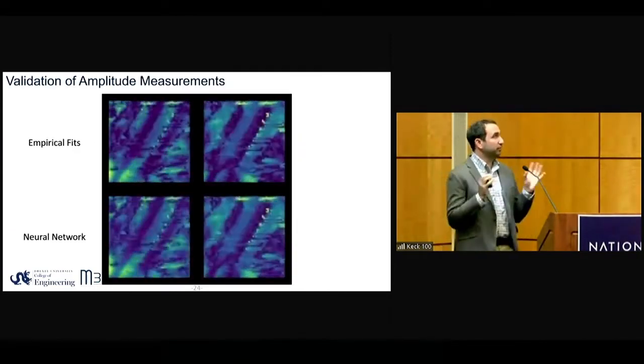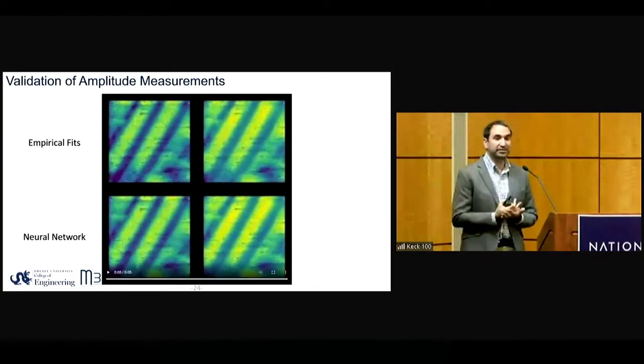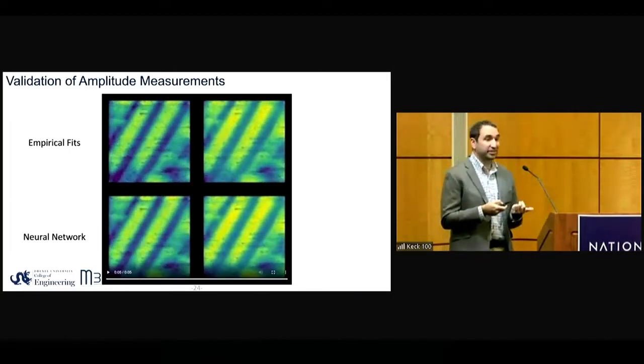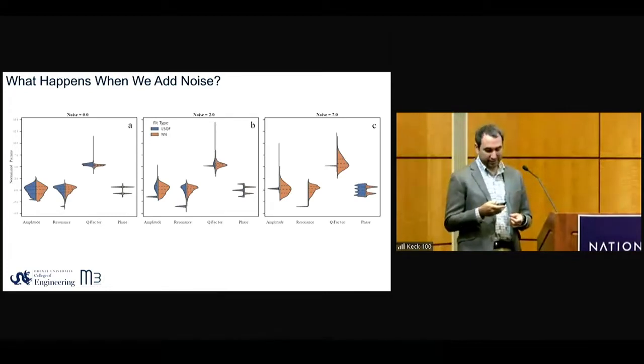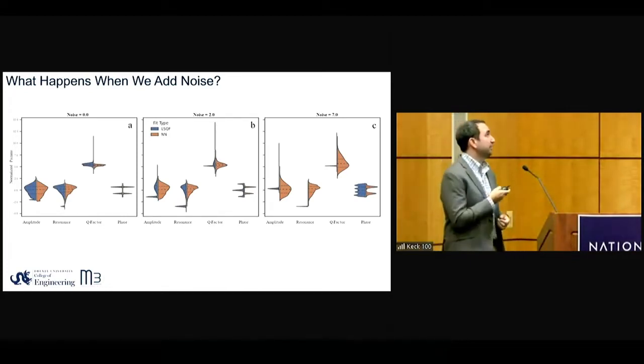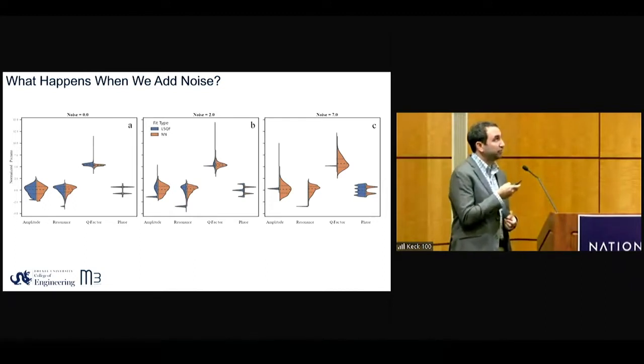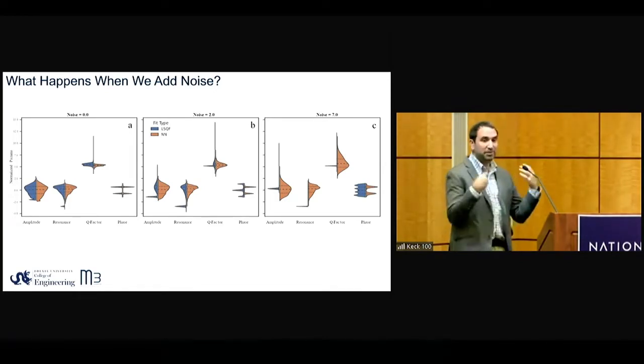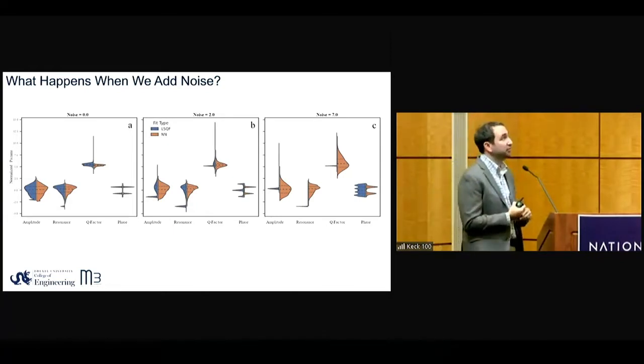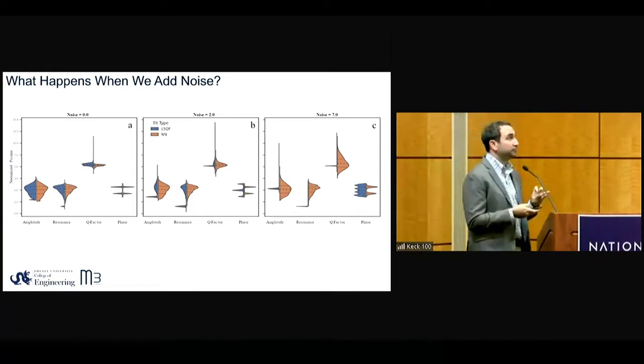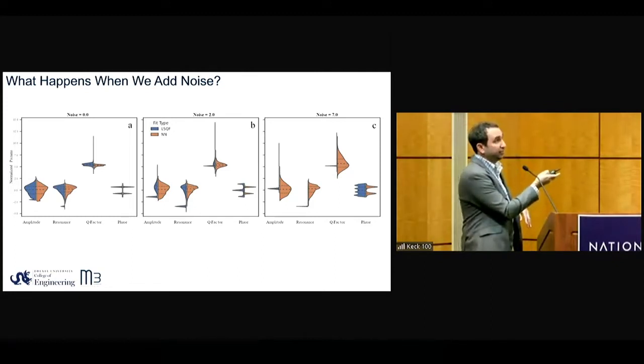If we look at the raw data that a person would extract, it looks essentially the same. There's no difference. So that's a good sign. But things get more interesting when you start to add noise. If you add noise based on the standard deviation of the raw data, you see that as you add more noise, the least squares fit tends to not fit the data at all. It gets trapped in a local minimum, and you end up not fitting your result well. You'd have to build in a lot more robustness to the model. This is a fairly robust, commercialized process. And you can see here the phase is completely irrelevant to the actual phase of the raw data, which is shown over here.